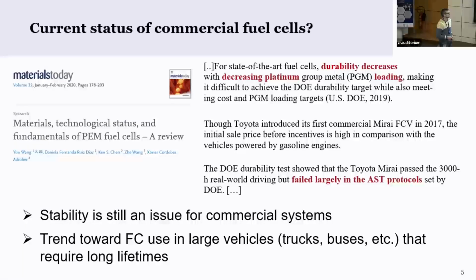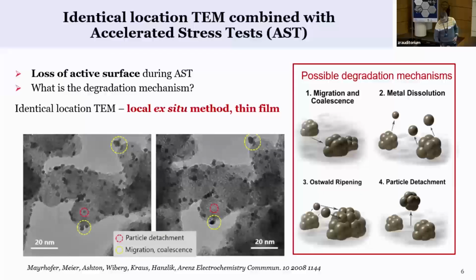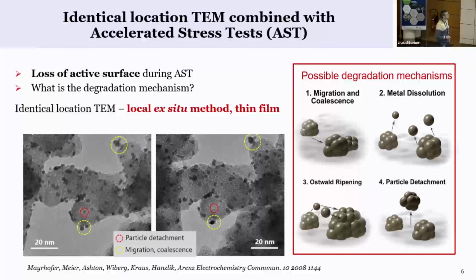And it's really difficult to predict lifetimes from a short test. So we like to do a test of a few days or a few hours, and then predict based on this the stability of different catalysts. And that's an almost impossible task. So when we started this field, we introduced microscopy methods to investigate degradation phenomena, where you could actually track the individual particles and how they react to such a stress test.